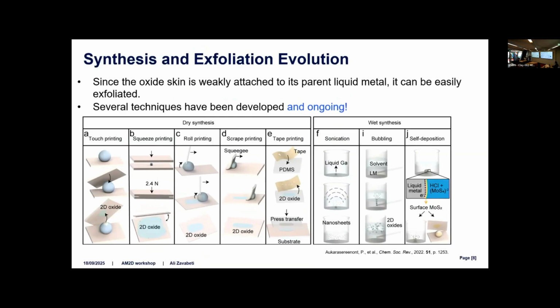Then we came up with a slightly larger surface area printing. We called it squeeze printing. So we can place a smaller droplet between two substrates and press them. As the droplet expands, it forms oxide, and at the same time, the oxide attaches to the substrate. So we can coat and print 2D oxides on this substrate.